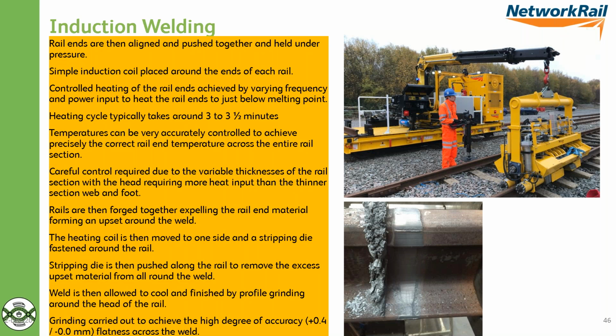This is the Mirage network rail combined machine, the latest guise of it. It looks a bit like a flash butt welder, but instead of using electrical resistance heating to heat the rail ends, effectively it clamps over the rail. It brings two disc-cut rail ends together, puts a force onto that, and then locally heats it using induction coils to heat the rail up to approximately 1500 degrees C. It takes about 3.5 minutes to reach that temperature. It then applies a constant force, and that effectively forges the ends together.